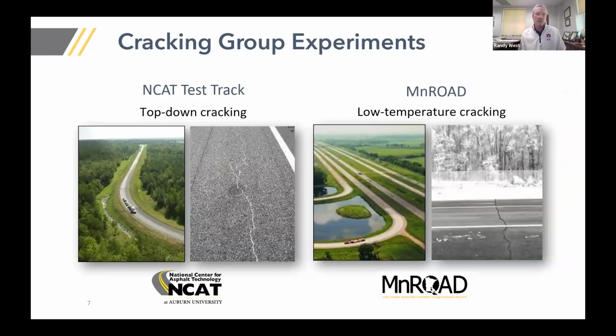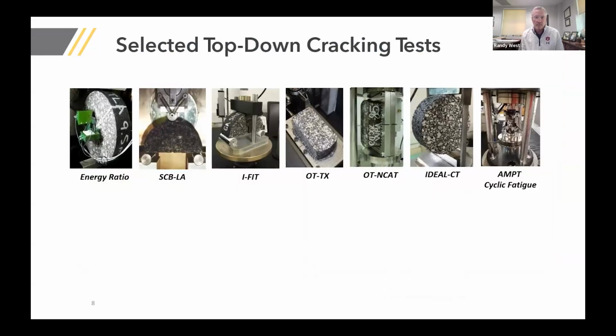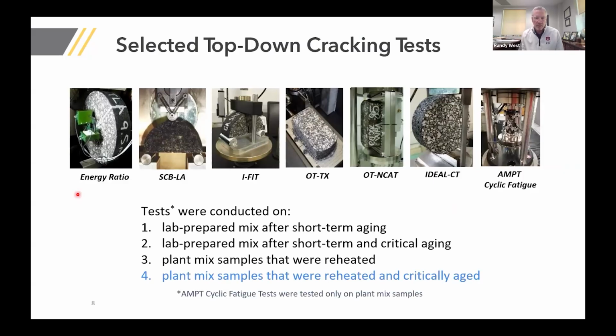So getting into this thing that we called the cracking group experiment was actually a partnership between NCAT and Minroad. NCAT, we were looking at top-down cracking, and there's 7 different cracking tests that we included in this experiment, and I'll go through each one of these. Not necessarily the test details, but I'll go through the correlation to the field performance. And we did these tests on both lab-prepared mix and plant-produced mix, and on samples that were short-term aged or plant-produced and those that were reheated. I'm only going to talk about number 4 there, the plant mix samples that were reheated after critically aging. And I apologize for the red laser. That's an artifact of an earlier presentation where it looks like it recorded that laser movement. So hopefully we won't see that again.